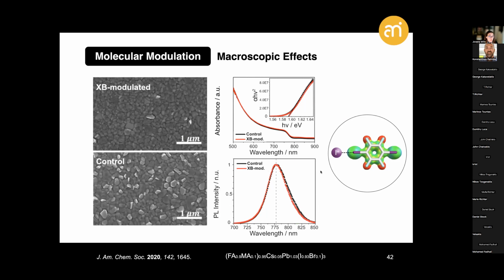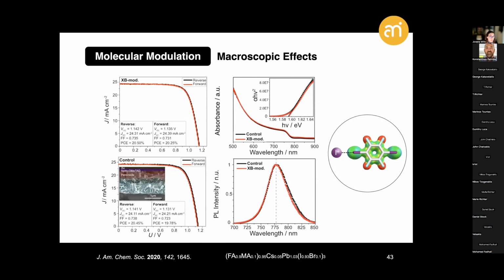This is, in fact, also the case for the photovoltaic performances, which are preserved as compared to the control samples. So in the presence of the modulators, we do not change the photovoltaic performances at all in these small quantities of modulators, inside the perovskite composition or at the interface with the corresponding hole transport materials, for example.